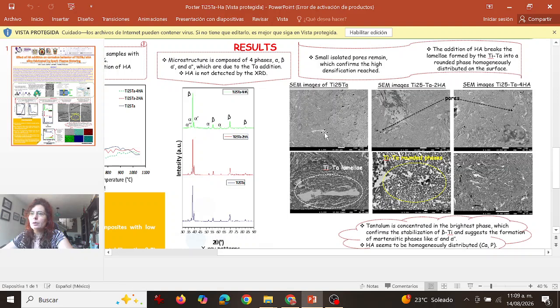If we do a zoom, we can observe that we have a titanium tantalum in a lamellar form. In here we can have a look, and we observe that we have small pores, and in here we can observe that the titanium tantalum after the sintering gets a more rounded phase, we can call it. See? So the conclusion was that small isolated pores remain, which confirms the high densification reached by the alloy after the sintering. And we also can conclude that the addition of the hydroxyapatite breaks the lamella formed by the titanium tantalum into a more rounded phase, and it's homogeneously distributed on the surface, as we can see.